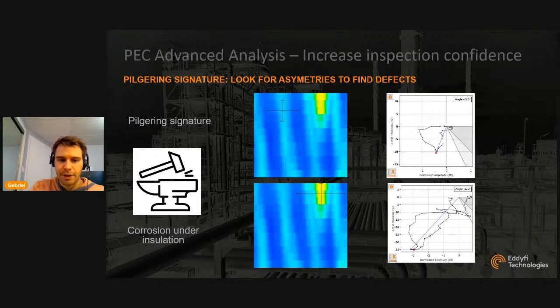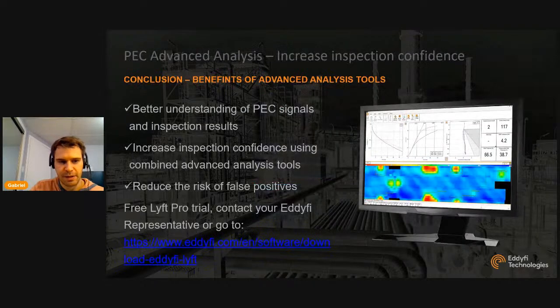But when you look at a real indication such as this one, then the real indications within the Pilger signature are also well identified as defects. So it's a case where you need to look for asymmetries in the C-scan to find defects, areas where you've got more wall loss or the wall loss is standing out from the pattern of the pilgering signature.